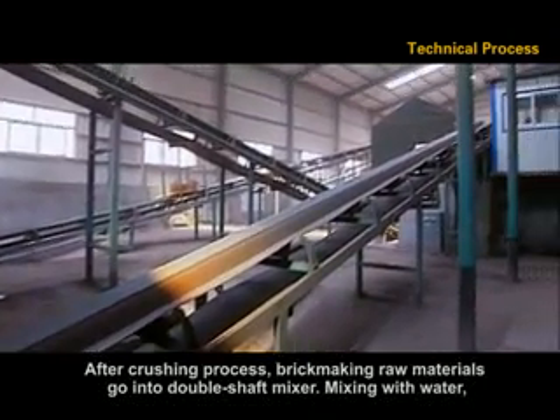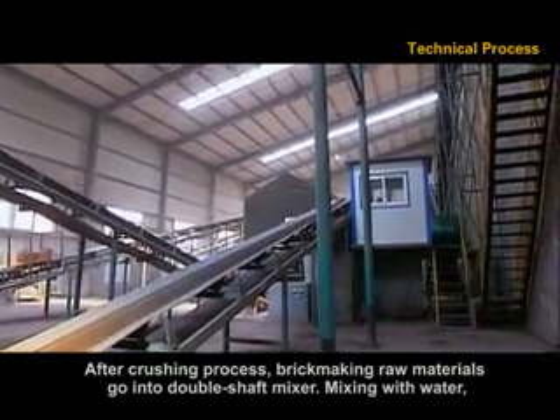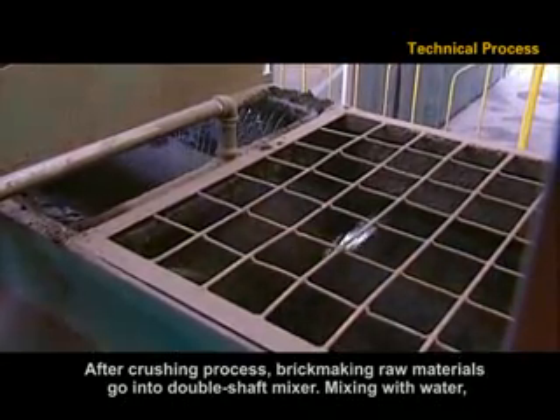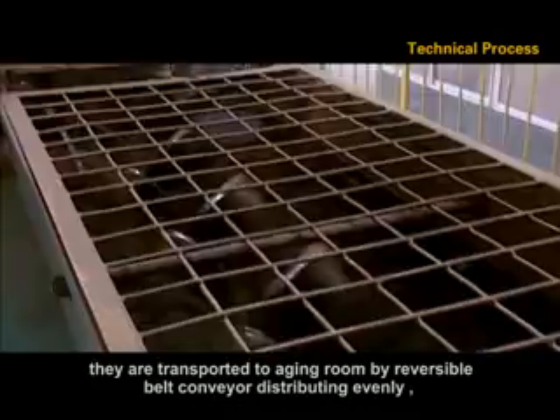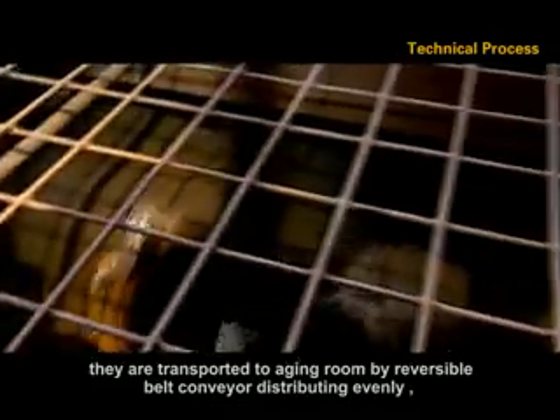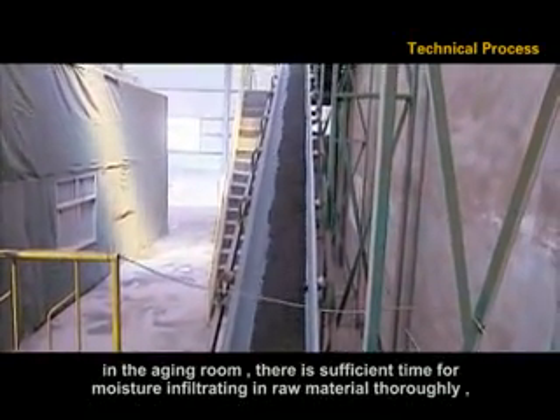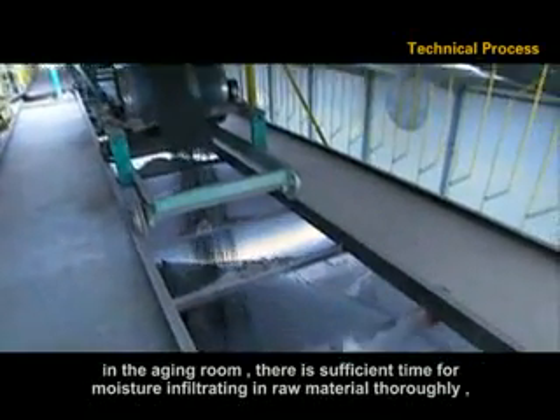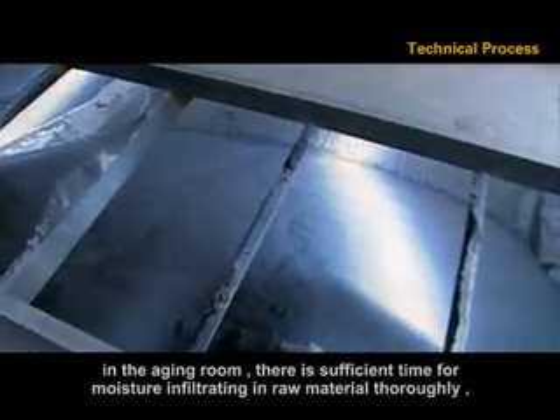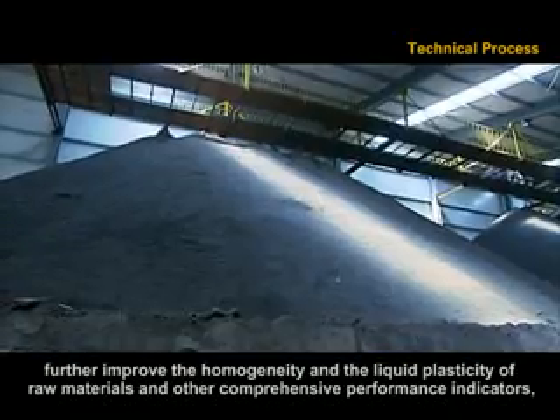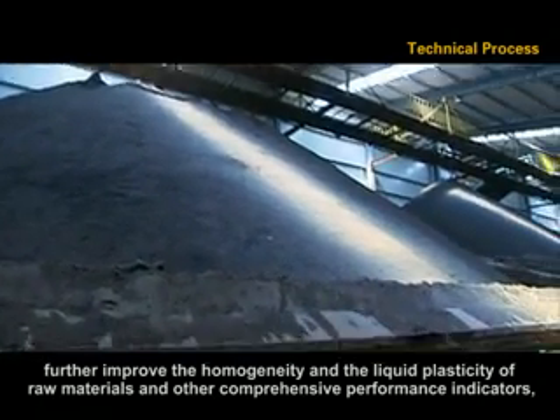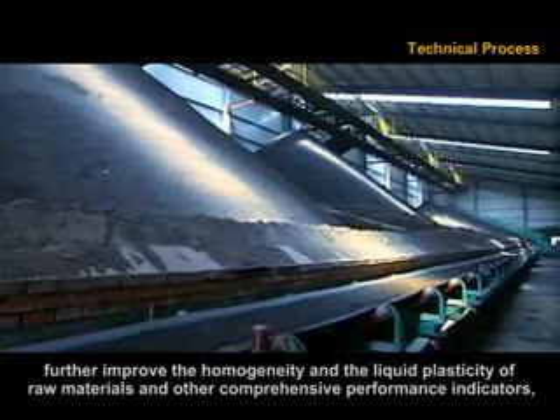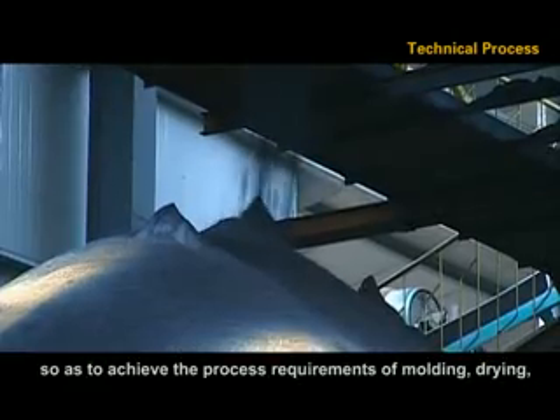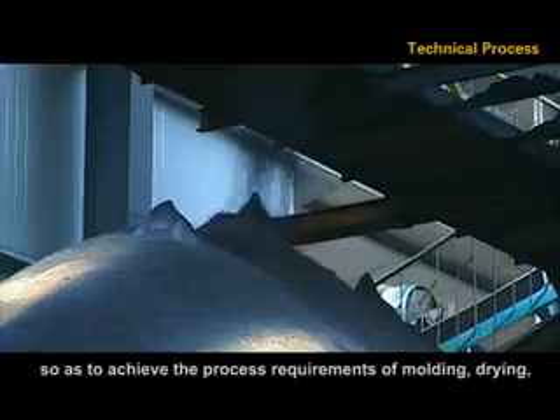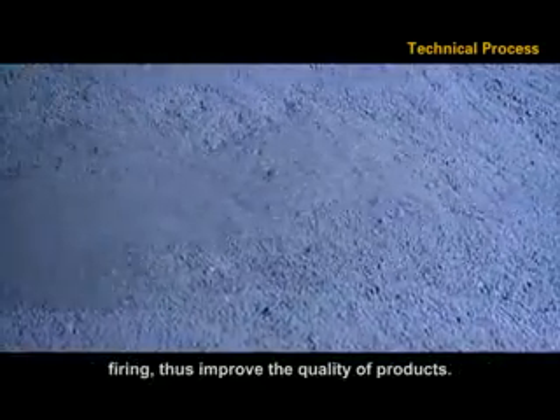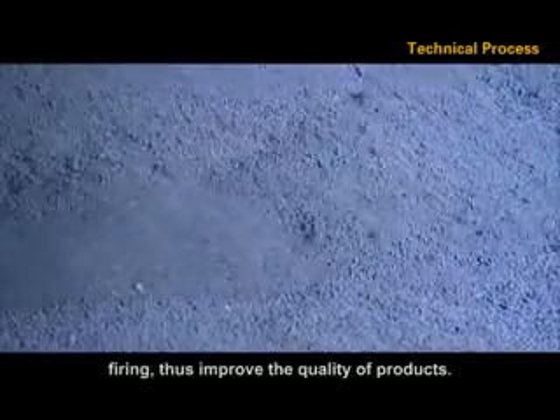After the crushing process, brick-making raw materials go into the double shaft mixer. Mixing with water, they are transported to the aging room by reversible belt conveyor, distributing evenly. In the aging room, there is sufficient time for moisture to infiltrate the raw material thoroughly, further improving the homogeneity and the liquid plasticity of raw materials and other comprehensive performance indicators, so as to achieve the process requirements of molding, drying, firing, and thus improve the quality of products.